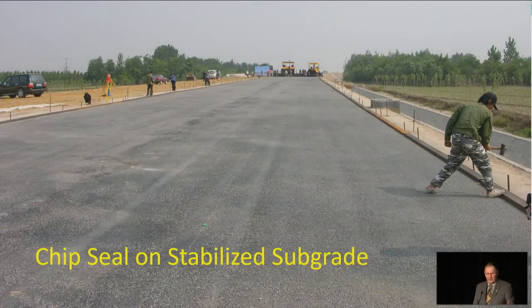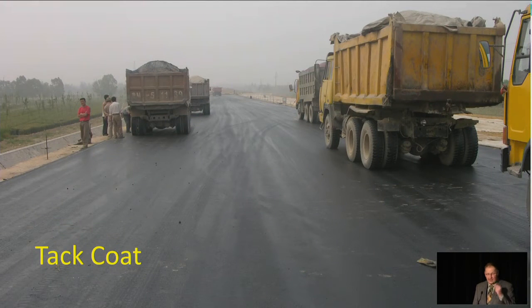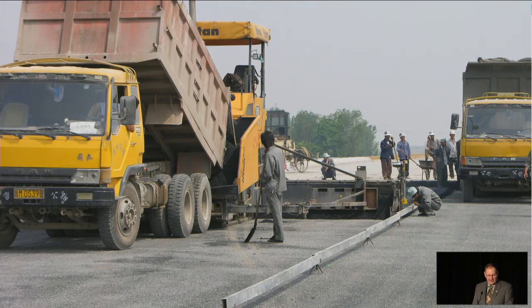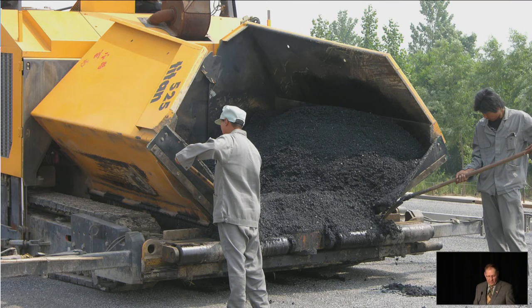Here we are out on the grade. So they chip sealed on top of the lime treated subgrade, and then they applied tack coat on top of that chip seal. There you can see the trucks lined up and ready to discharge their mix. They used echelon paving, so they had 2 pavers to pave the full width of inside shoulder, 2 lanes, plus outside shoulder. So they paved all at once.